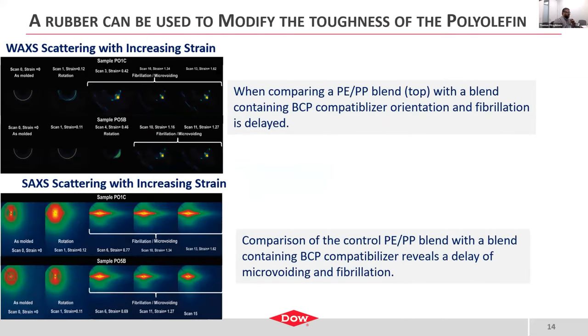Well, we add that rubber modified material, but we don't just add the rubber modified material. The rubber modified material, the elastomer, doesn't necessarily interact well with the polypropylene matrix. So oftentimes we need to add some sort of compatibilizer, a block copolymer type material that will compatibilize the polyethylene-based rubber material with the polypropylene-based matrix material. And that has a big effect on what we observe in the wide angle and small angle X-ray scattering data. If we look here at the very top, this is an unmodified, no compatibilizer, polyethylene polypropylene blend. And you see that similar lamellar rotation followed by fibrillation followed by microvoiding event.